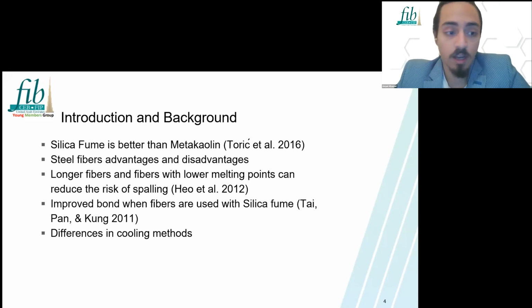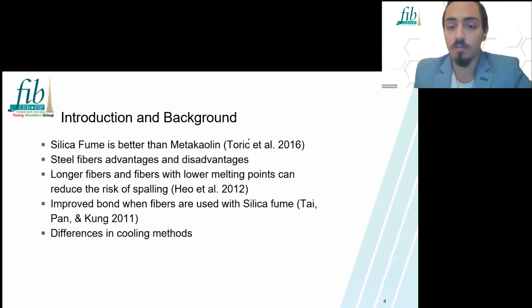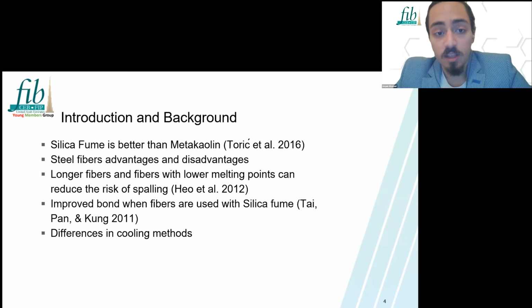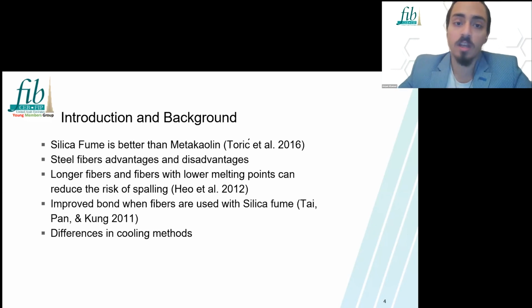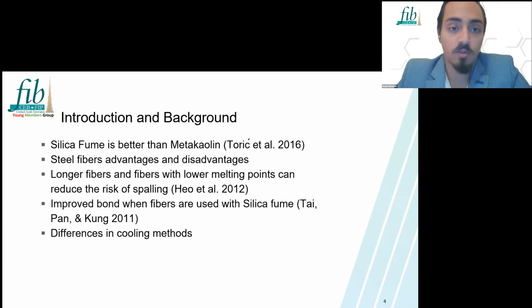And one clear variable in the literature was the difference in cooling methods. Now, many people are using air cooling or cooling naturally, meaning taking the samples outside of the furnace, leaving them on the side without applying any air or any water, just letting them cool in room temperature. This is fine, but you also need to study water cooling, because it is more representative of real life cooling. Because when the firefighters come, they don't just sit there and wait for the fire to cool on its own. They pour water on it, or they use fire extinguishers. So there are different types of cooling. Each of them will give different results.